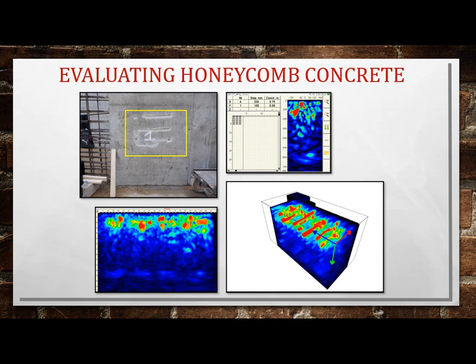And so what this is telling us is the red is rebar, the yellow would be weakened concrete matrix, so honeycomb, blue is sound concrete. And then at the very bottom, the bottom left picture, there's like 4 lighter blue. That actually shows the backside of the concrete. So you can measure the thickness plus or minus an inch with this unit also.